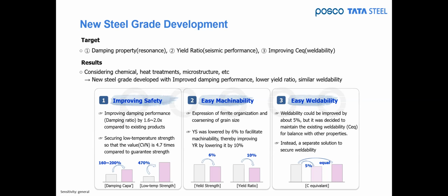The second issue was that there's going to be a lot of welding, drilling, cutting, a lot of machinability. To assist that, it would be good to have a better yield ratio. So we looked into the actual structural part. Do we need to go higher in strength, or do we need a better yield ratio? We found that the loads in a Hyperloop currently do not require higher strength. So we should go to a better yield ratio. Lowering the yield ratio means better formability, and you'll be able to do a lot of manufacturing and other processes with it. About 10% was improved accordingly.